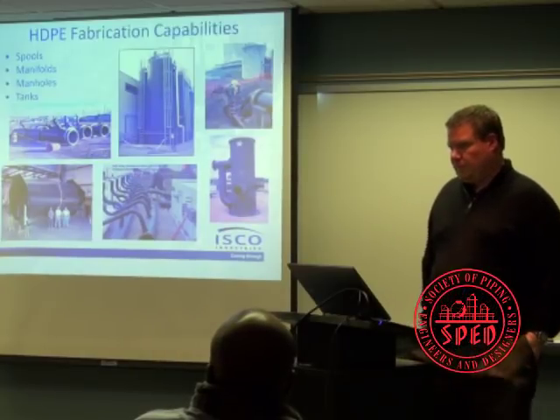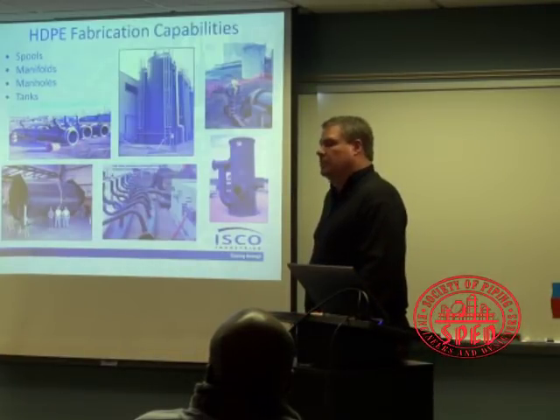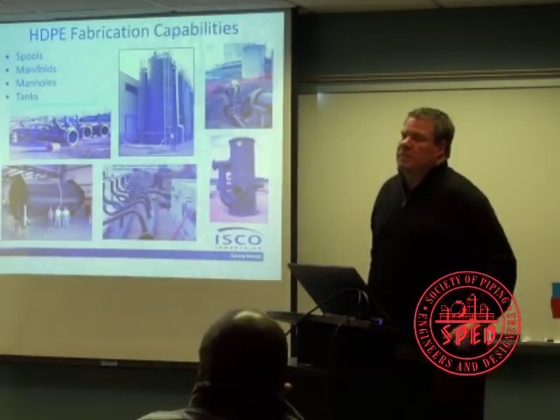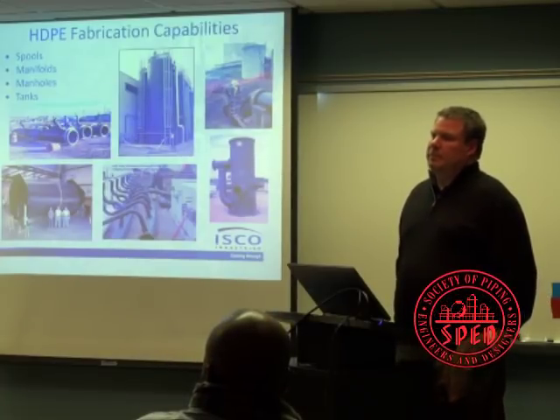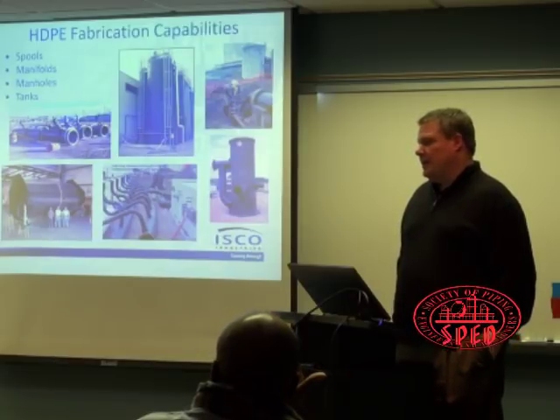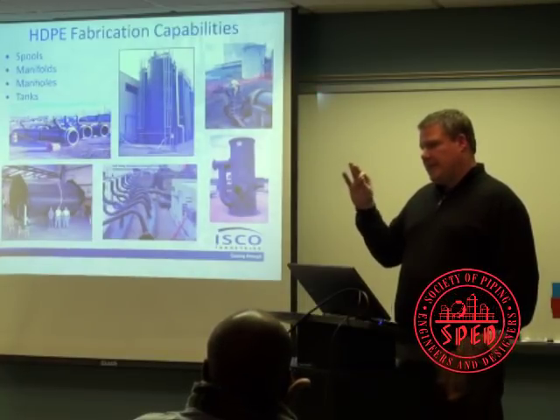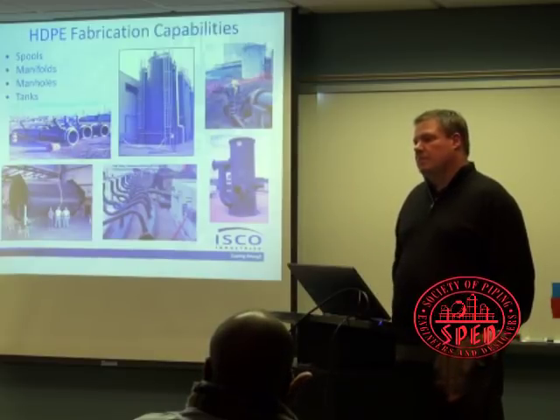I've used it a lot in the past with companies that have neutralization tanks, where your pHs are varying. A lot of this pipe is above ground. You have to be more careful with the support, but it works real well for, like you said at the very beginning, varying pHs that you're going to run through. If you've got corrosion issues, it might be something to look at. I'm not going to say polyethylene for every job. It's got a temperature range and pH range, but it's going to fit 95% of those jobs out there and do it very well. And I've used it in double-walled sumps in ground,